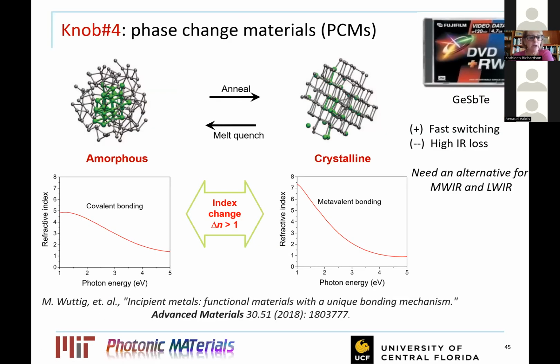So the last thing I'm going to talk about is some of the work we've done over the last 5 years as part of a DARPA-sponsored project on phase change materials. And for those of you that aren't as familiar with phase change materials, in our case, these are chalcogenides again, but they're alloys. And what's unique about these alloys is once they're deposited into thin film form, they start out amorphous, but upon a stimulus, whether it's thermal or electronic, we can convert them to a crystal and then retransform them back to their amorphous state.